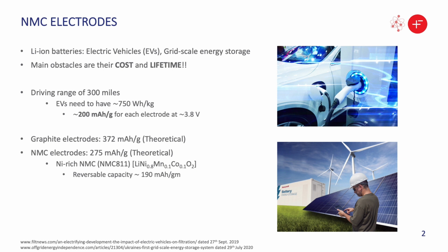Now let's look at the electrode choices that we have. Regarding the negative electrode, graphite has been used traditionally, and it has a theoretical capacity of 372 milliamp hour per gram. There are several choices for positive electrodes, and recently it has been observed that NMC electrodes have a theoretical capacity of 275 milliamp hour per gram, which is as high as it gets for any positive electrode currently in the market. However, the reversible capacity of NMC electrodes, especially the nickel-rich NMCs, is around 190 milliamp hour per gram. This reduction in reversible capacity is because we cannot extract all of the lithium present in the NMC electrode.